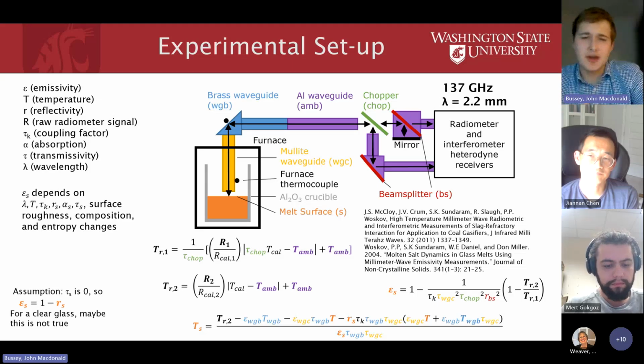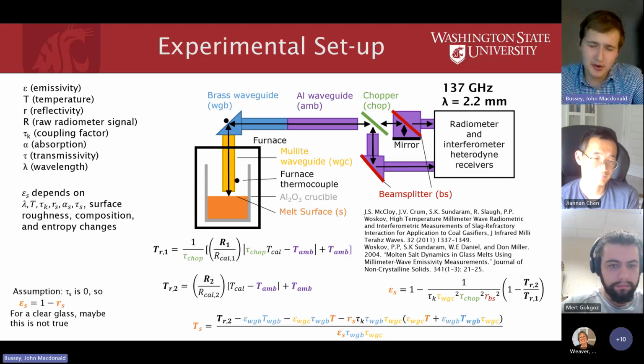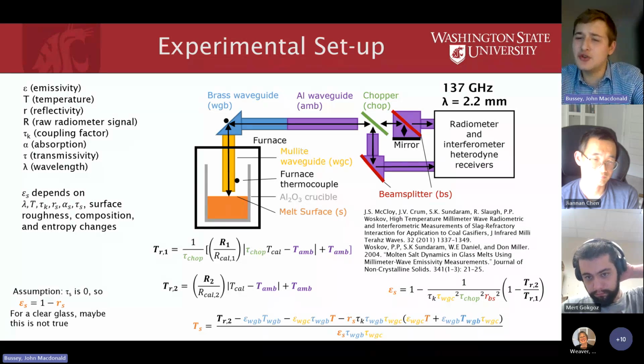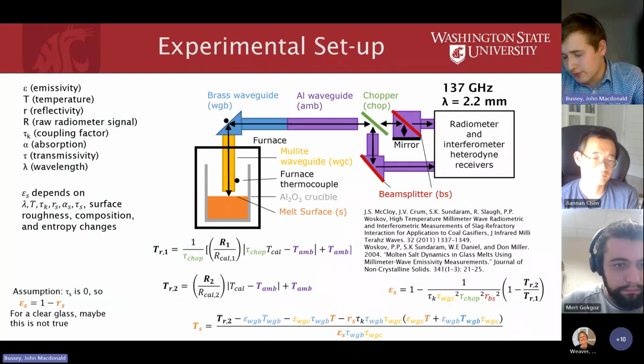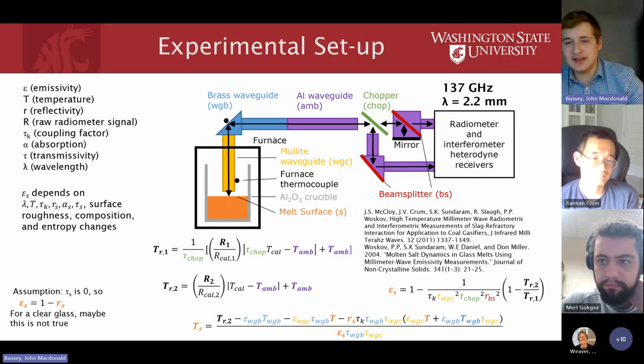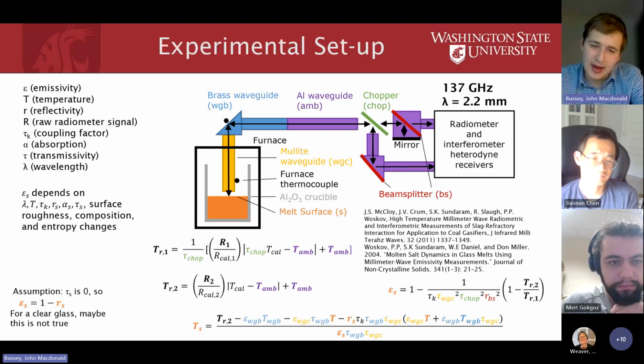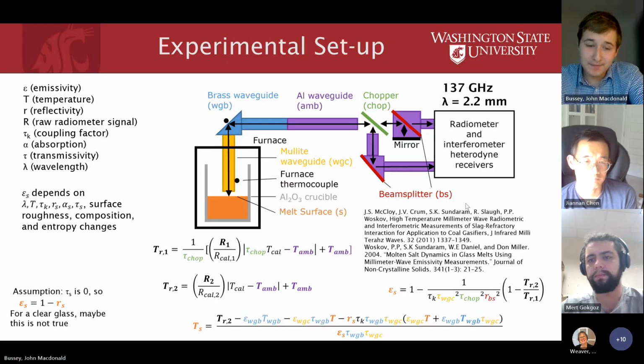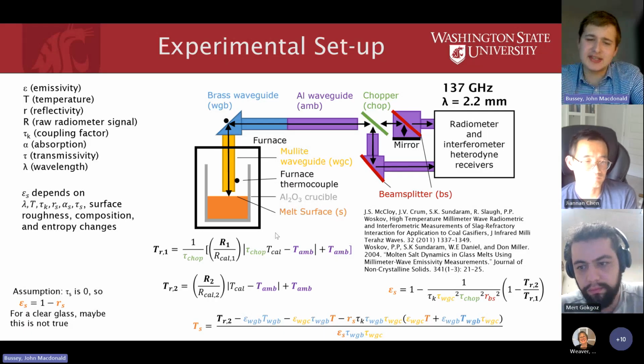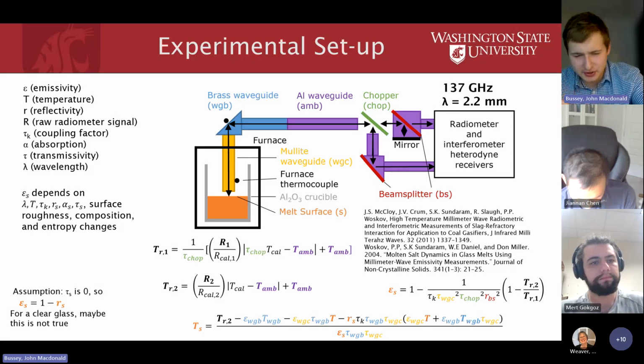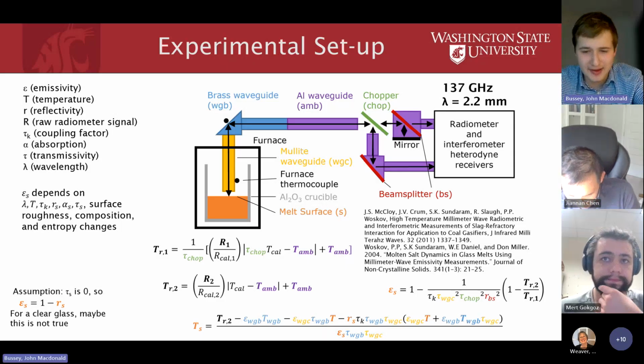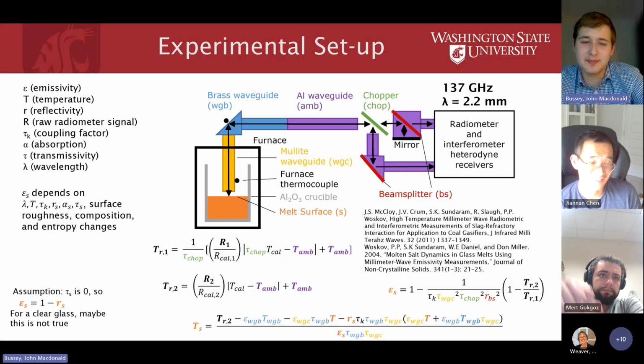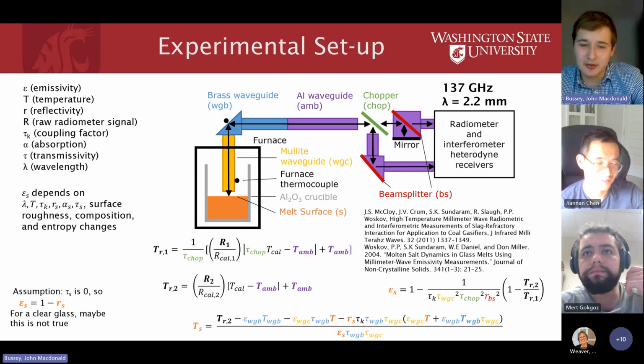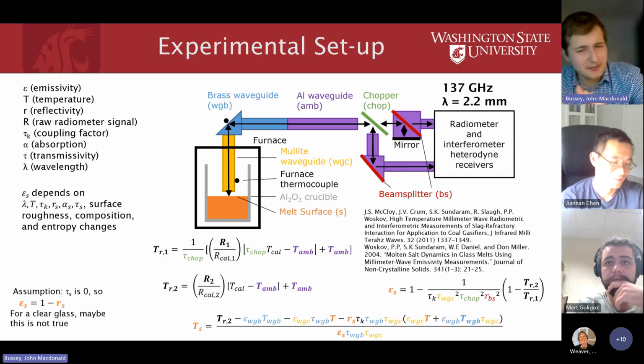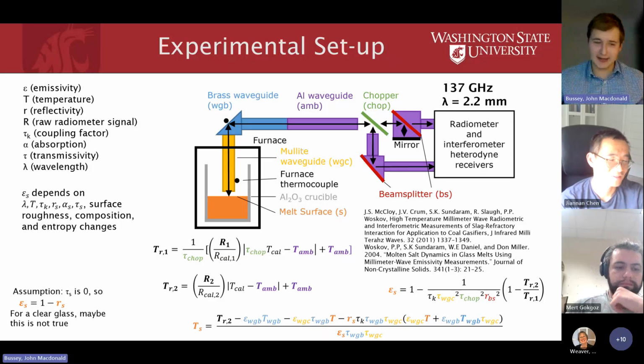So we're not going to do that, but the key point here is different optical components add complexity to the system. And then we have two radiometer receivers, which is important because based on knowing the difference in the length that they travel, we can gain information on what the emissivity is. And you put the two radiometer values in these equations with some calibration constants and some known constants and the temperatures that we measure. And from that, you're able to back out emissivity. And then from that, you're able to back out a measured temperature of the sample with the radiometer. And of course, we can measure the temperature of the sample with a thermocouple, and so we do that to compare against.